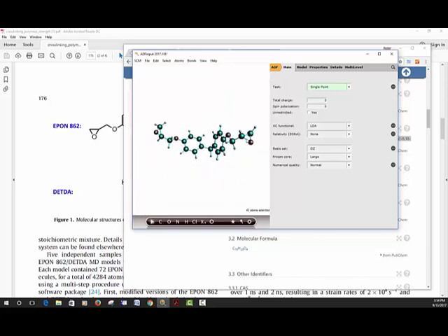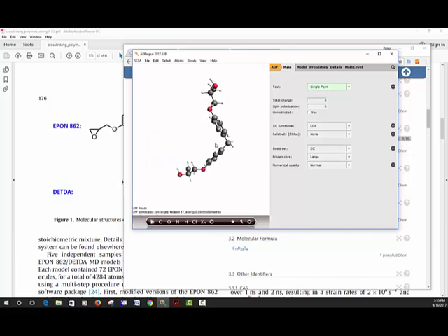Now this epoxy agent, when it polymerizes, has a ring opening polymerization, and those epoxy rings will open. They form two alcohol groups, so we delete those bonds, add hydrogen atoms to the oxygen atoms by pressing Ctrl E, and we clean up the structure a little bit by pressing this cogwheel here, which does a UFF optimization, universal force field.